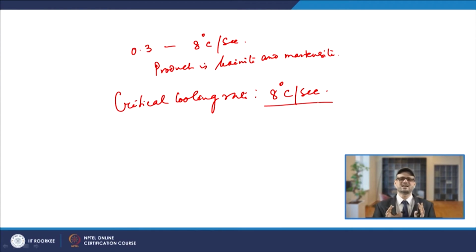So what you see is that if you add the alloying elements, that's why alloyed steels have more hardenability. These alloying elements are basically shifting the curves towards the right, and with continuous cooling, which in the normal case without alloying elements in the steel, it is very difficult to get the martensitic structure. In the case of TTT diagrams we saw that you have to isothermally hold it and then you get that structure.